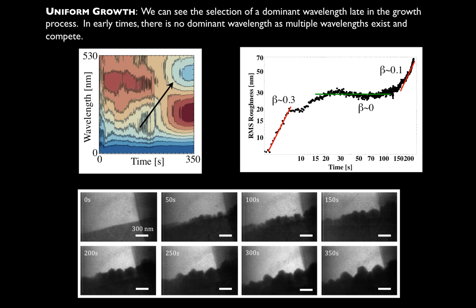Understanding the transients of which wavelengths are dominant is a very difficult mathematical problem we're still working on, but we do expect the wavelength to grow with time. If we were to let this go on forever until we reach steady-state conditions, the wavelength in this type of copper electro deposition would be 50 microns — something we can't even probe with our window size. But we can begin to see what's happening with these shorter wavelengths that are interacting in the early time, and that's what's leading to this roughness growth.